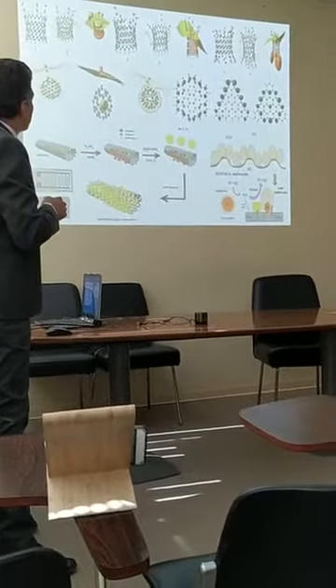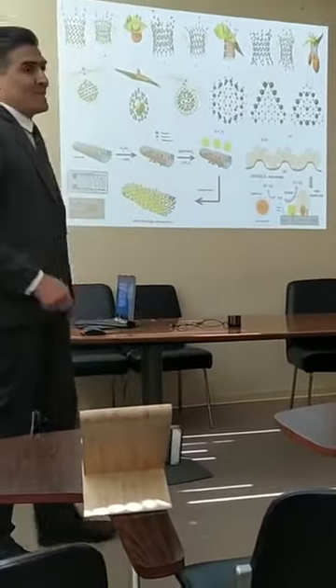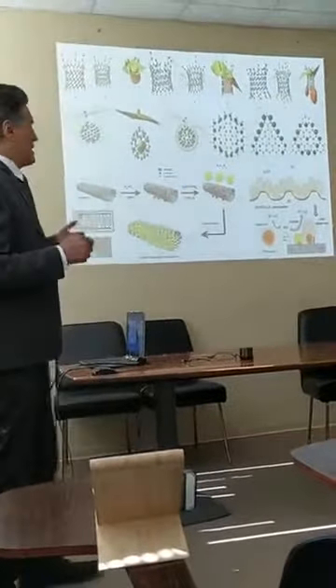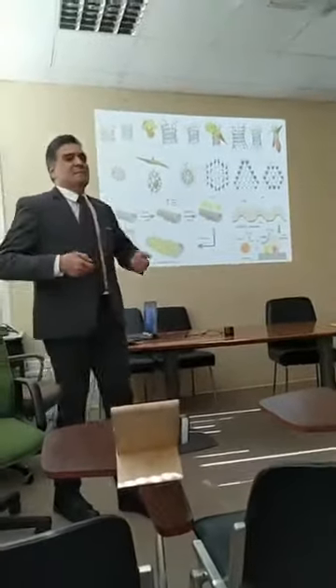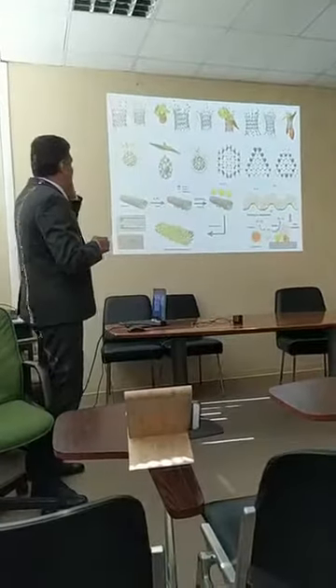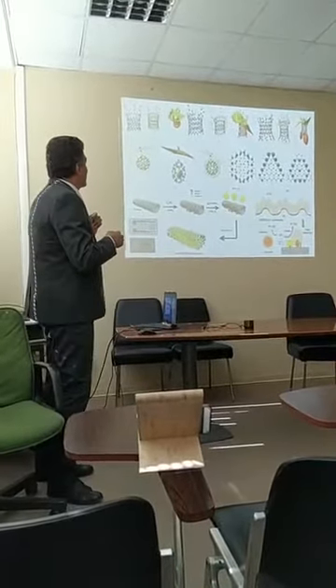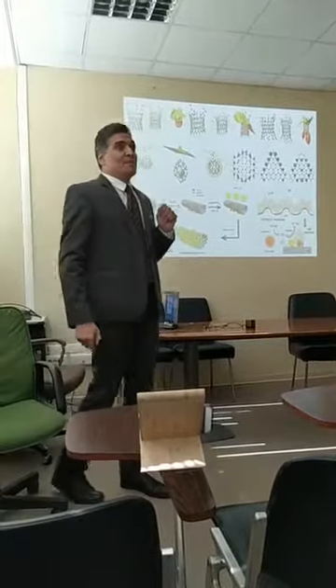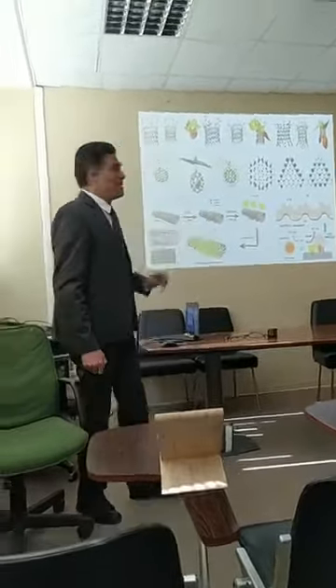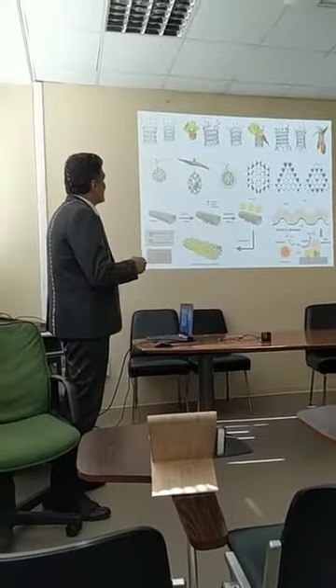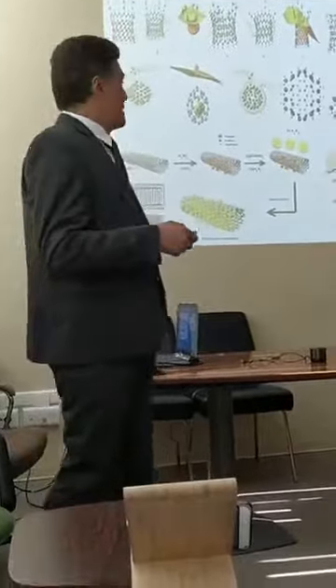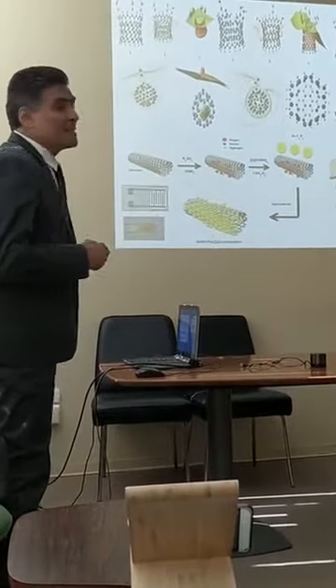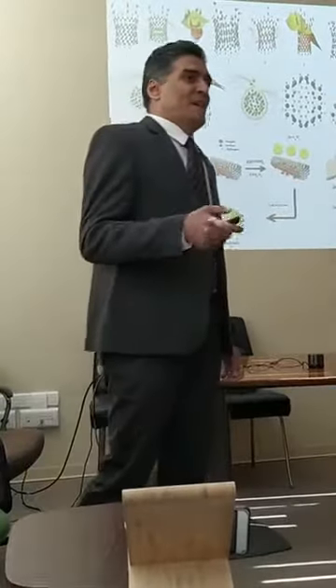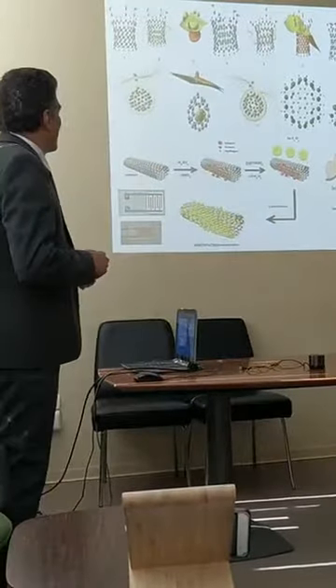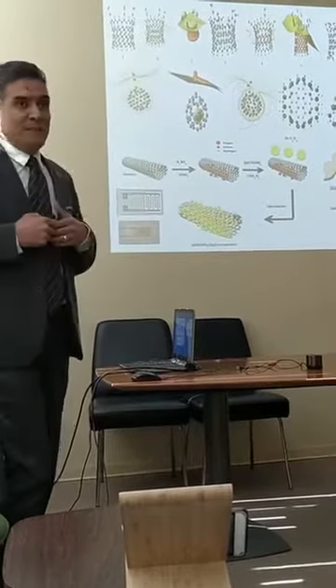This is a single wall carbon nanotube decorated with metal oxide. Actually, metal oxide itself could work as a gas sensor, but it needs some kind of activation. If you put the carbon nanomaterials with the metal oxide semiconductor, it could work at room temperature, so we save energy. We have tried different schemes. Each scheme is in one of our published papers, and then we study even the electrostatic potential to know where the active site is, where the metal could go, or where the volatile organic compound can go, and then we can go to our colleagues working in experimental work.